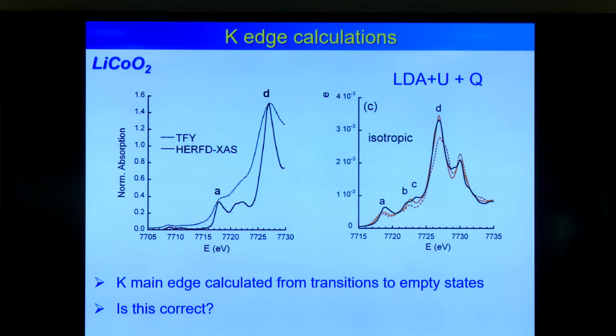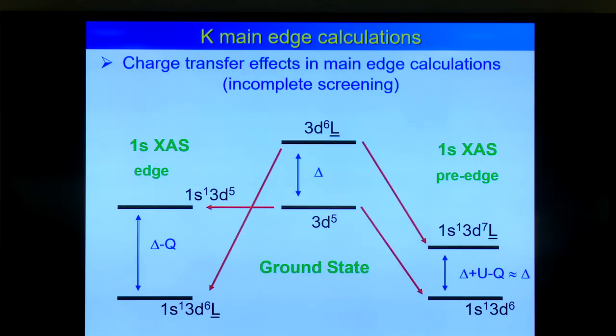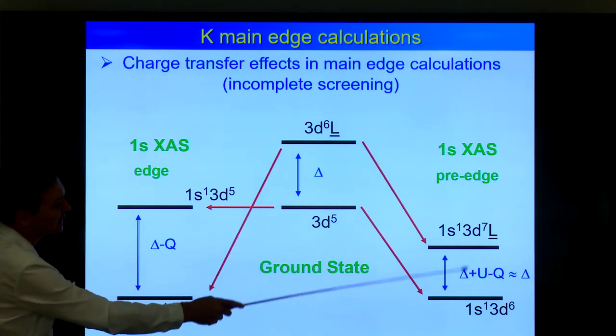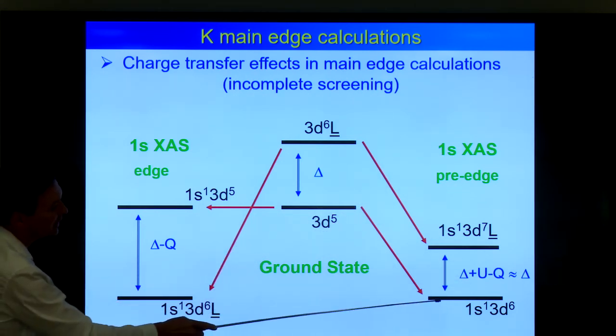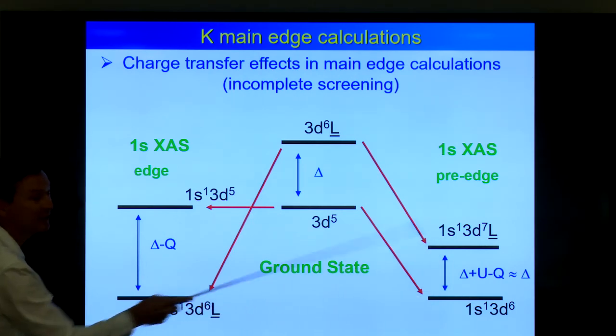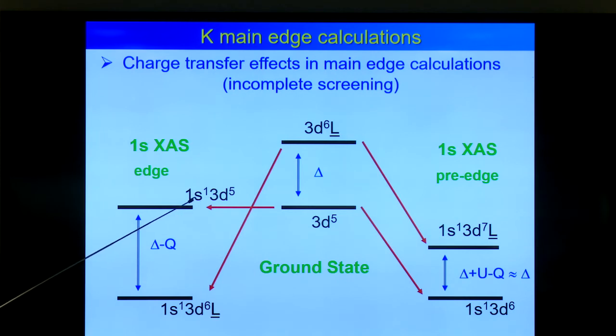But then the question is, should this be the correct way of calculating a K-edge? And then I come back to this graph again, but now instead of doing X-ray photoemission, I put here 1s X-ray absorption pre-edge, and then you do a quadrupole excitation directly to the d-band, so this is a self-screened process again, so you can do multiplet calculations. If you go to the edge, you excite the 1s electron to a p electron, which I assume to be the same as a free electron. So your d5 goes to 1s1 3d5, but the d6 ligand hole goes now down by the core hole potential. So now you have two configurations, at least two configurations, which are important for your calculation. So which one should you take when you do your DFT calculation?